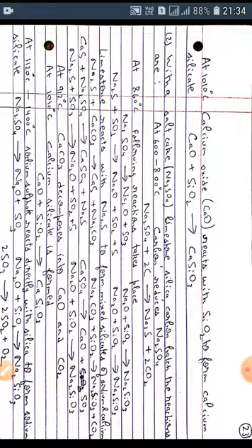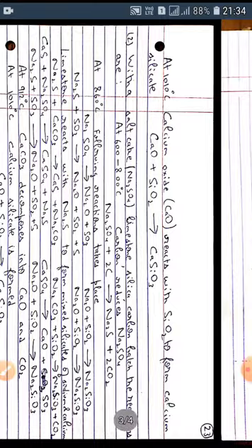At a temperature of 912 degrees centigrade, calcium carbonate decomposes into calcium oxide and carbon dioxide. Again, at a temperature of 1010 degrees centigrade, calcium silicate is formed by the reaction of CaO plus SiO2 gives CaSiO3. At a temperature range of between 1120 degrees centigrade to 1400 degrees centigrade, sodium sulfate reacts directly with silica to form sodium silicate. That's Na2SO4 gives Na2O plus SO3. This Na2O reacts with SiO2 to give Na2SiO3, and sulfur trioxide decomposes into sulfur dioxide and oxygen.